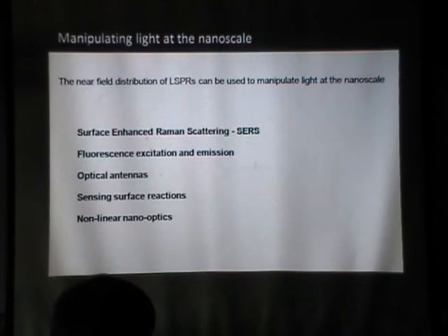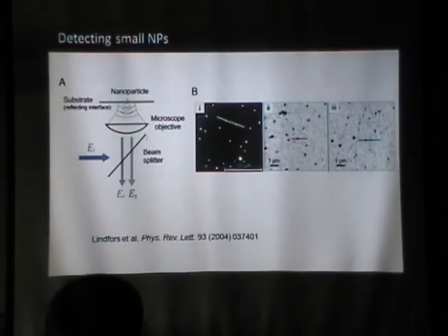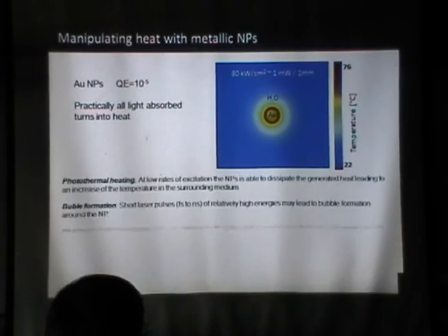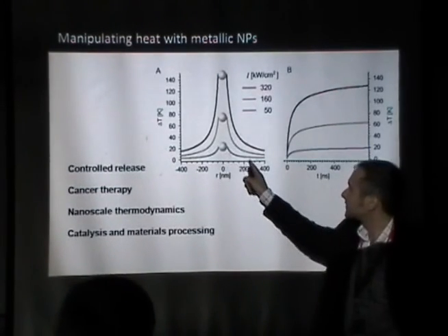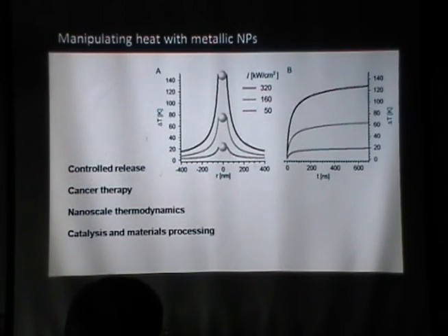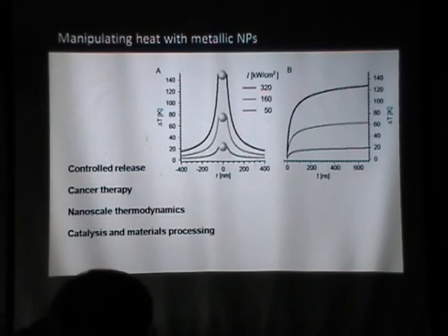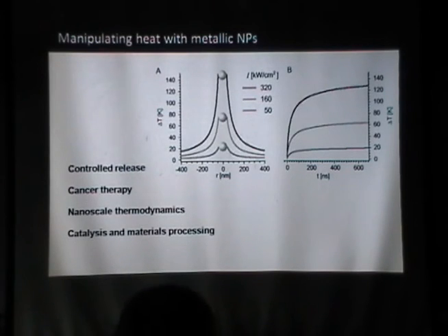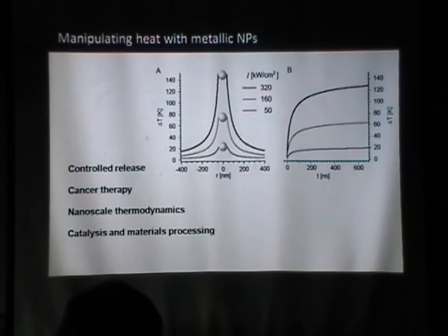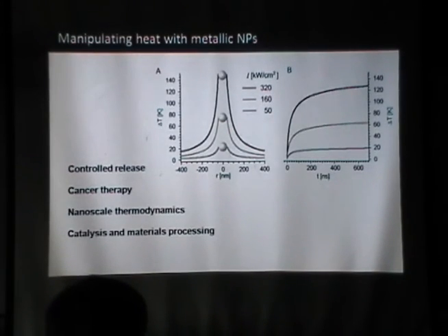Are there any experiments somebody tried to measure something similar to the temperature? Yes, people have tried, but if you look, the region that you're heating is very small. So after 200 nanometers, there's nothing. And there are no methods currently to measure temperature at such a resolution. If you use higher laser intensities, then the region can be visible. People have done it, for example, using temperature sensitive dyes, and then they can see how the color changes or the spectrum changes. But that is when this region gets to some microns, and then they can extrapolate to lower laser intensities.